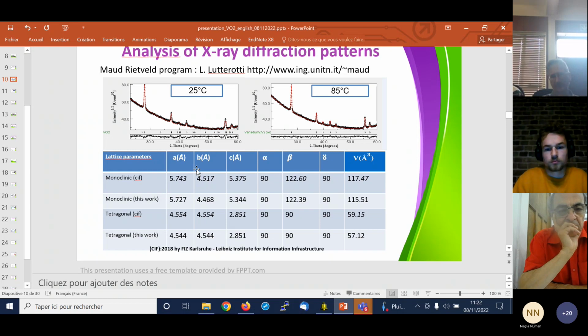Okay. So another question, maybe a stupid one from an experimental point of view: when you do doping experimentally, do you have control on the percentage of doping, or you just dope and then you measure? No, as I was saying, we were not the ones making the films. They were made at the CEA, and those guys made very careful experiments to measure the exact content of the doping by Rutherford backscattering.